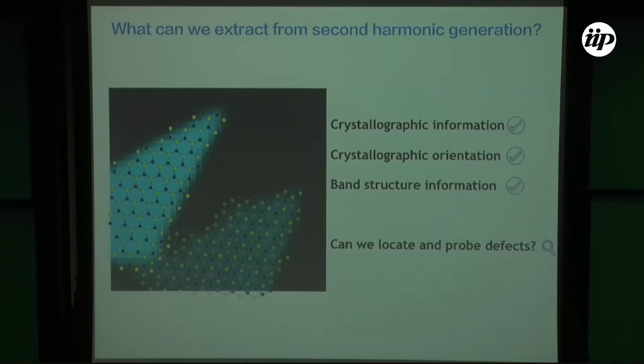So this was back in 2013. Last year, or maybe 2 years ago, a lot of different groups started to use this kind of technique to find the crystal orientation of different TMDs and start putting them together. So to summarize this part, we can know the crystallographic information and orientation of 2D materials. We can also know some band structure information. I'm not showing it here, but we can do what we call resonant second harmonic generation, where we tune the laser energy and probe different excitons in these materials.